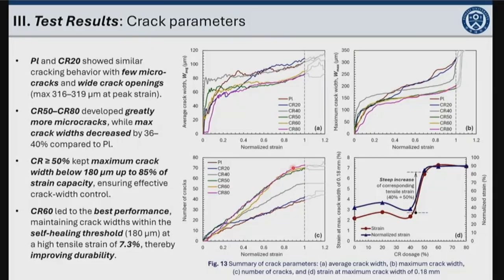The CR60 sample showed the best cracking performance with the smallest crack width, and it successfully maintained the crack width below 180 micrometers, which is the self-healing threshold, up to a very high tensile strain of 7.3%.